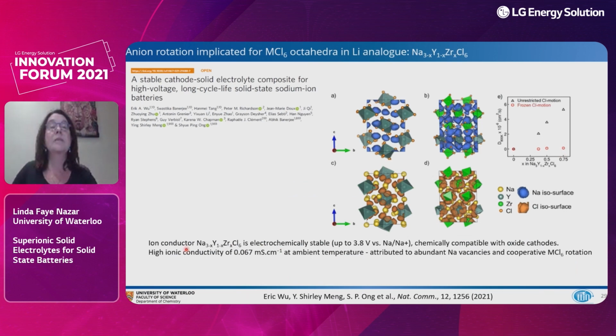And so this ion conductor is, like the other halides, stable to quite high potential, in this case to 3.8 volts. It's chemically compatible with the oxides in their naked form. The ionic conductivity in this case isn't quite so high, but it is higher by 2 orders of magnitude than the pure yttrium, in other words, the non-zirconium-substituted phase. And this effect, this 2 orders of magnitude conductivity, is attributed to both the vacancies and the really intriguing anion rotation that I mentioned earlier in the talk. We haven't looked at this in our lithium analogs yet.